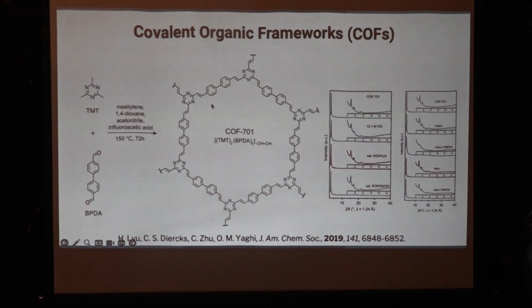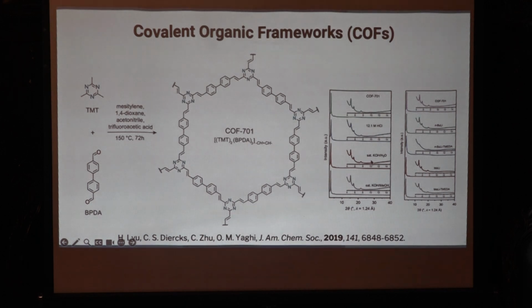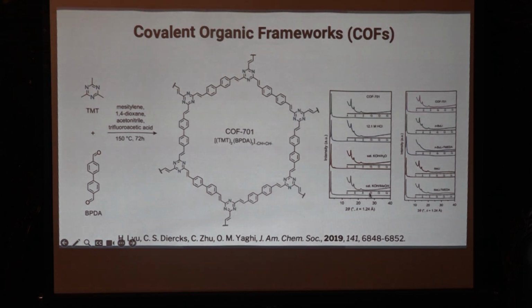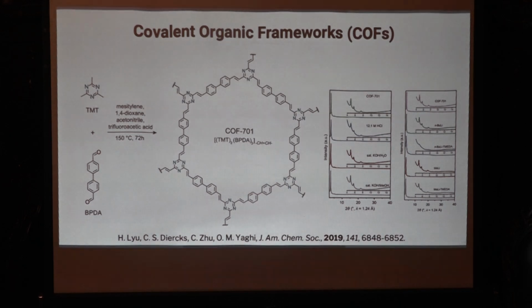It's a long story. But nevertheless, if you look at the backbone, there are carbon-carbon bonds and carbon-nitrogen double bonds. Very strong bonds. Nothing will destroy this material. As you can see here, when we expose it to acid, 12 molar HCl, saturated KOH, the material is maintained. You can see the diffraction line. It stays crystalline. So this is a wonder. It's a wonder material. Okay?